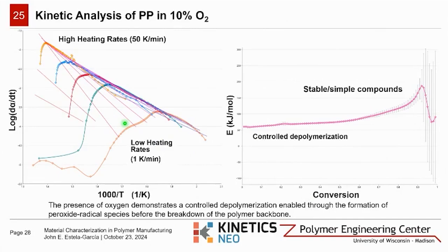In our kinetic analysis of polypropylene degradation in a 10% oxygen environment, the Friedman method fails to provide consistent results across different heating rates, particularly as we're approaching complete conversion. And this is simply due to the complexity of the reactions that take place.